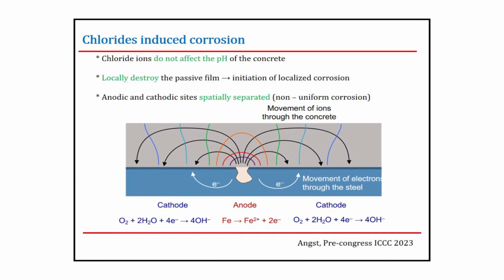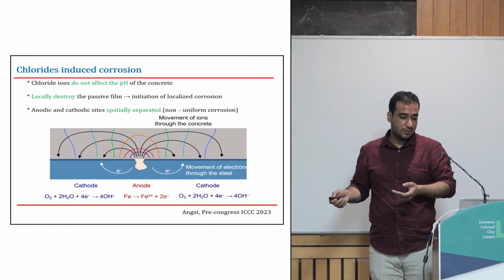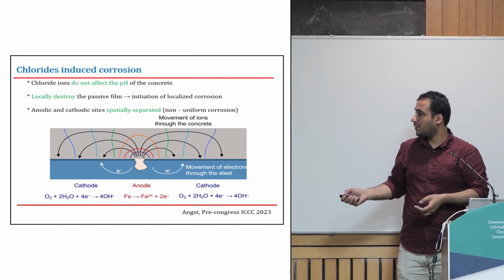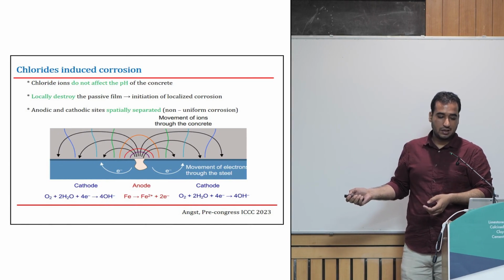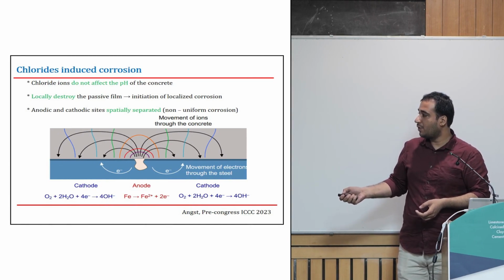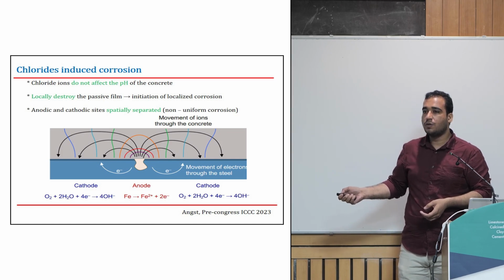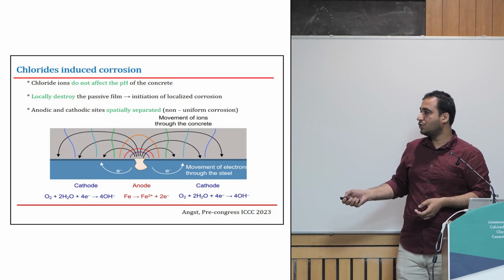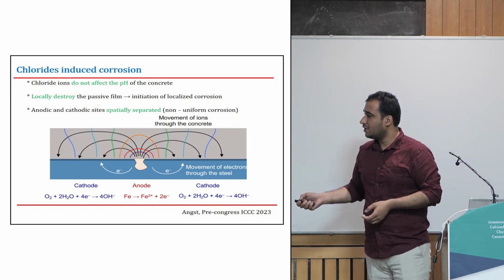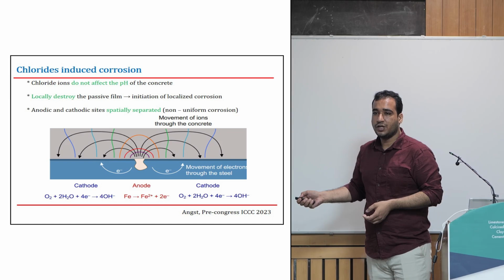Now coming to the chloride induced corrosion, it is different from carbonation. Here the pH of the concrete is not affected throughout the concrete. Chlorides penetrate into the concrete at the same pH, but they destroy the passive film locally at one point, and anode and cathodes are formed. The anode is limited to this pit only, whereas the cathode is the whole rebar. So you see there is a high ratio of cathode to anode area.